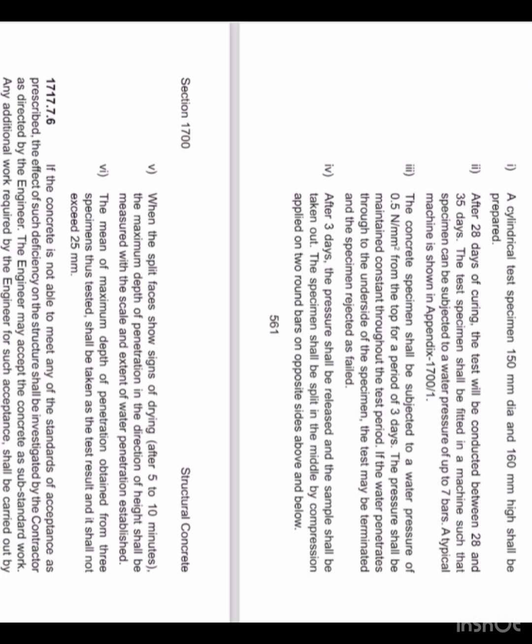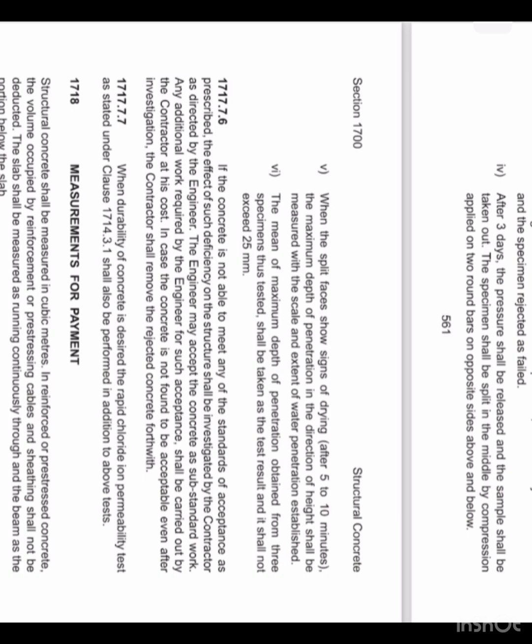The specimen shall be split in the middle by compression applied on 2 round bars on opposite sides above and below. When the split face shows signs of drying after 5 to 10 minutes, the maximum depth of penetration in the direction of height shall be measured with the scale and extent of water penetration established. The mean of maximum depth of penetration obtained from 3 specimens thus tested shall be taken as the test result, and it shall not exceed 25 mm.